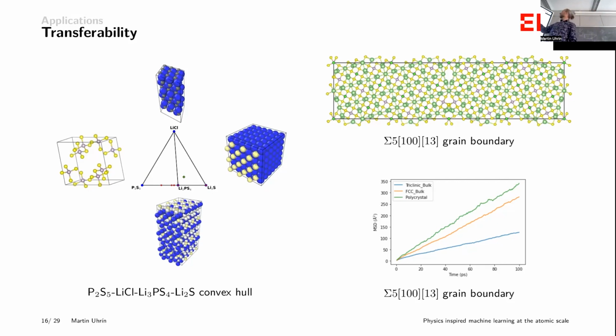But in reality, it's also possible because for now, we just measure the conductivity averaged across this whole thing. You also have diffusion that can go along the grain boundary. And it's likely that this is at times easier than actually trying to cross the boundary itself. So that could be contributing to this overall result. The next step is to, of course, pin this down exactly, look at the transport longitudinally and along the grain boundary, and then try many different grain boundaries, see if we can actually understand statistically what it looks like and correlate that with what's going on in the real material.